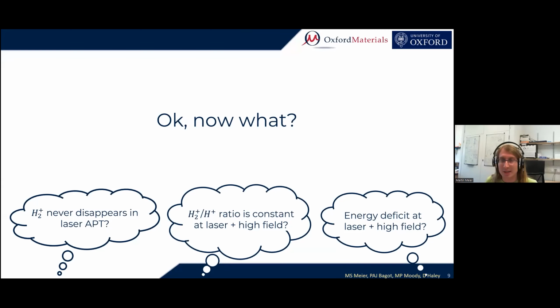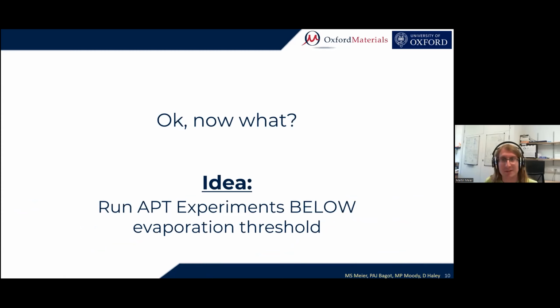And then we could really see when it is transitioning from what we would call the normal behavior into this unusual behavior. What is triggering it? And what else could be relevant parameters here? So what we want to do is control the electric field at which our tip is running. The common way of doing that is changing the laser power, because if you have a higher laser energy per pulse, then your tips usually run at lower electric fields. But for our experiments, we thought there's actually something smarter we can do.